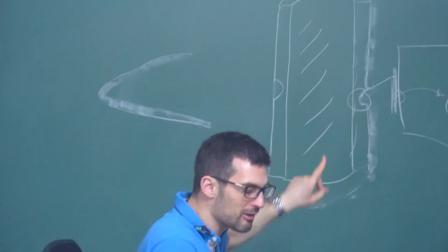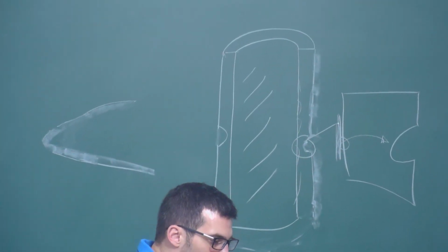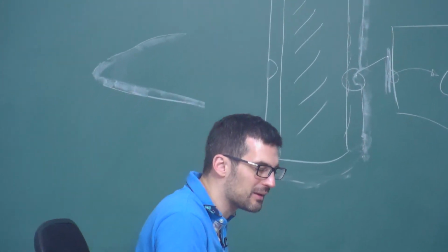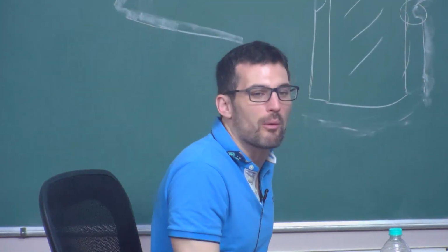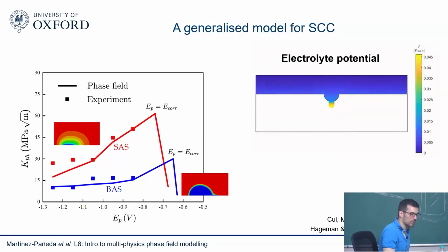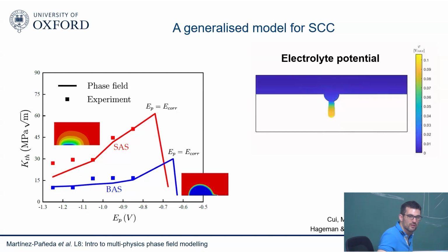What was interesting is that he predicted failure to occur after, I'm speaking by memory, but I think it was like 11.2 hours. In our model, where we tried to do things without any fitting, we predict failure to occur after 10.9 hours. So it was a small difference, but we tried not to fit. We could have fitted the model to get the same answer. We tried not to fit, and we put in all the numbers before running the simulation, so we got quite close.